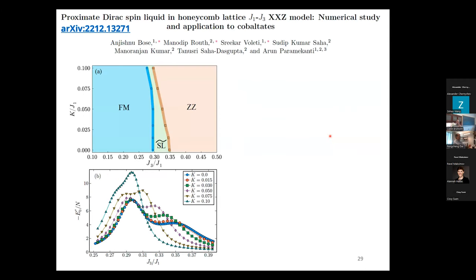There's another paper I wanted to call your attention to by Arun Paramekanti and his group, in which they have used DMRG to examine that particular J1, J3, XXZ model. And what they find is very interesting. When they plot the phase diagram as a function of J3 over J1 and Kitaev over J1, there's a window that opens up between the ferromagnetic and the zigzag phase where there might be some kind of a Dirac spin liquid phase, according to their parton theory that they also promote. And it turns out that barium cobalt arsenic oxide actually lies right in this regime here.